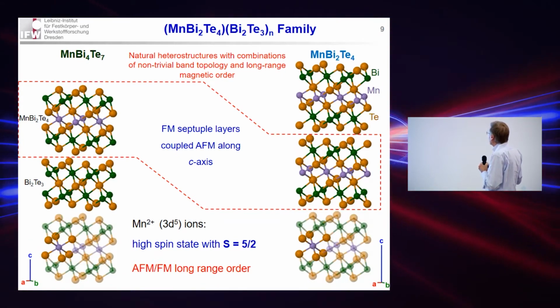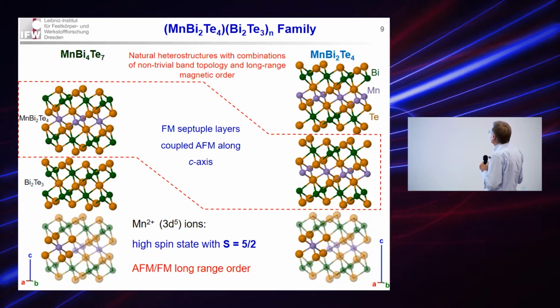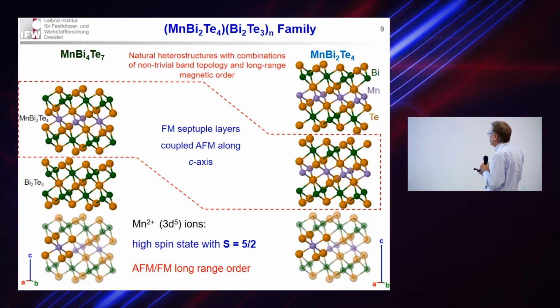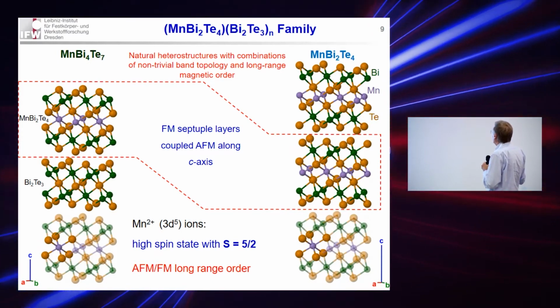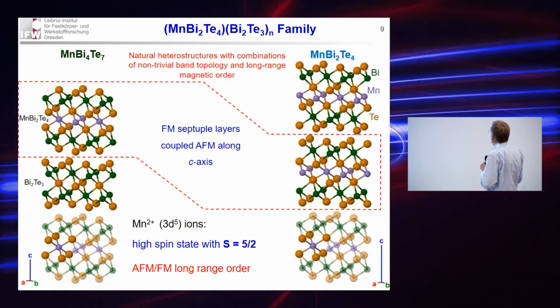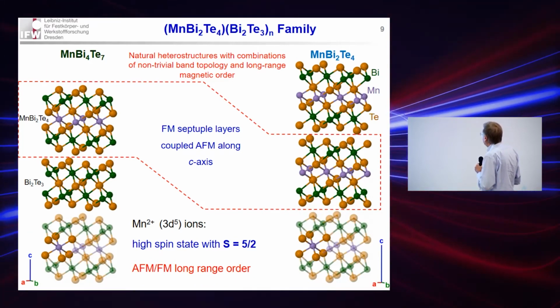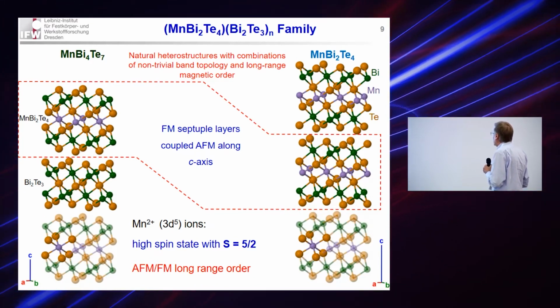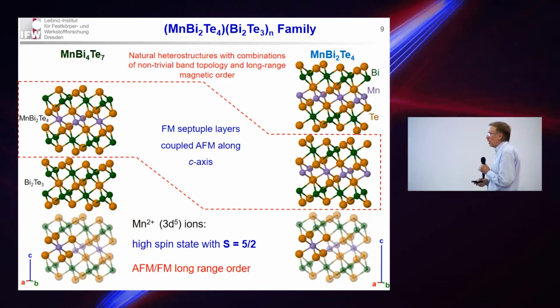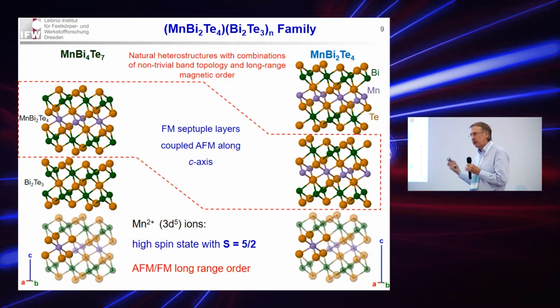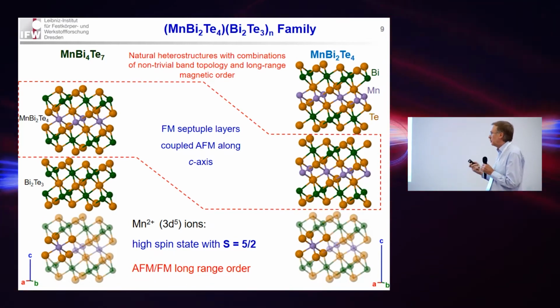of these septuple layers. That means quintuple layers of bismuth telluride with a double layer of manganese telluride. And they are spaced along the c direction and are coupled only by weak van der Waals forces. So it's a magnetic van der Waals compound.